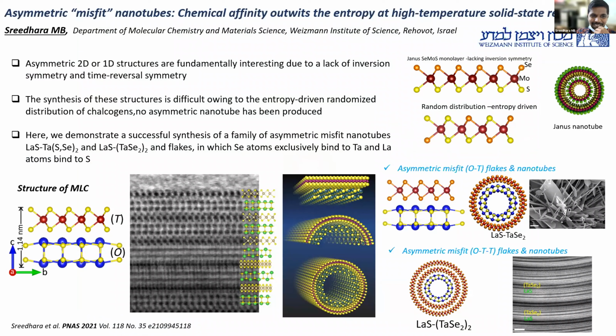Asymmetric 2D or 1D structures such as molybdenum sulfur selenium nanotubes and flakes are very interesting due to the lack of inversion symmetry and time reversal symmetry. But synthesizing this kind of structure is fundamentally difficult because, as you know, it's an entropy-driven reaction, which produces a randomized distribution of sulfur and selenium in the lattice at high temperature. No such 1D nanotube has been produced up to now.